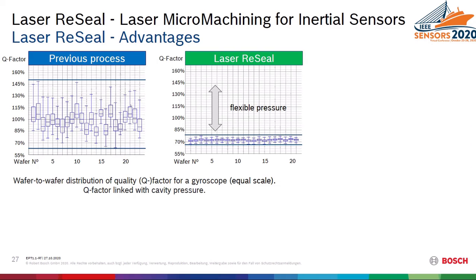So what are the advantages of the process? From our point of view, it is the enabler for both efficient and high-performance inertial sensors. On the left-hand side, you see the state-of-the-art encapsulation process, and the pressure inside the gyroscope cavity has a large variation between wafers and also inside each wafer. In contrast, on the right-hand side, there's the laser reseal. So you see a dramatic improvement of this pressure variation. And since the pressure is directly linked to the sensor sensitivity, we also get a very homogeneous sensitivity. And the good thing is that you can even flexibly adjust the pressure. So this gives us an additional degree of freedom for the sensor design.